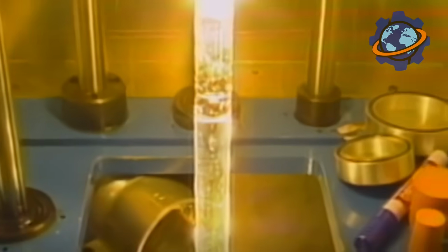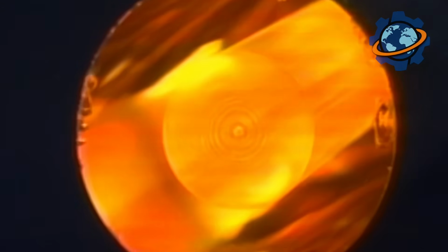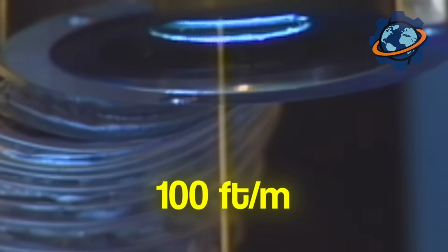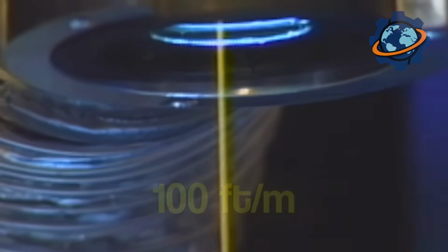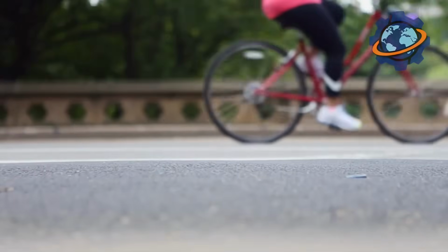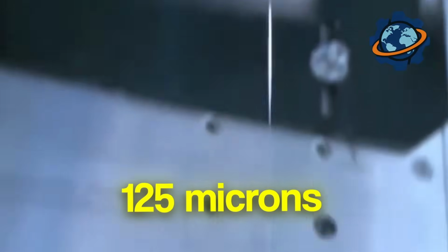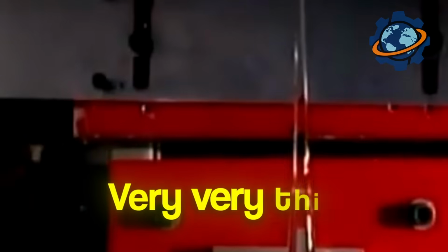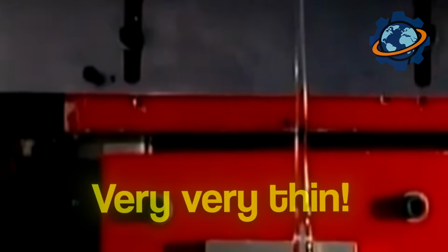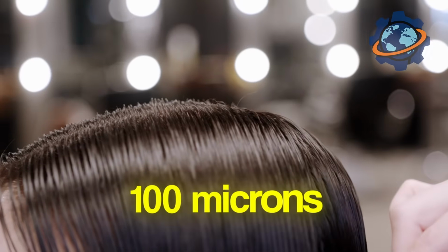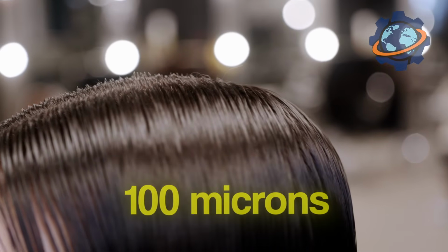This thread, the optical fiber, is drawn at a speed of approximately 100 feet per minute. Imagine that. It's faster than a cyclist moving through the city. It's important for the thread to be of uniform thickness throughout its length. The thickness of an optical fiber is usually around 125 microns, or approximately 0.005 inches. That's very, very thin. For comparison, the average human hair is about 100 microns thick or less.